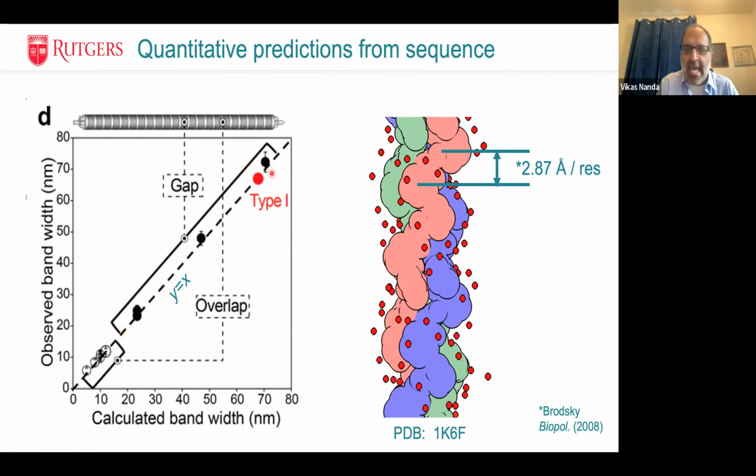And here is animal collagen, that type 1 collagen with the 67 nanometer banding. And with an ABC insert, we can get very close to that with these synthetic collagens. So we can access these morphologies that are on the same scale as biological systems.